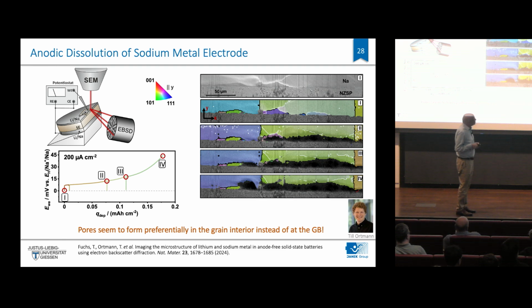And also what we saw is that, in fact, all the pores seem to have their nucleation not at a grain boundary, but really in the grain interior. And the explanation is pretty simple. The grain boundaries are fast. And if you create a pore at a grain boundary, the transport is so fast that it probably doesn't grow. But if you go into the grain where the diffusion is slower, the pore nucleates and can grow because the diffusion into the pore is slower.